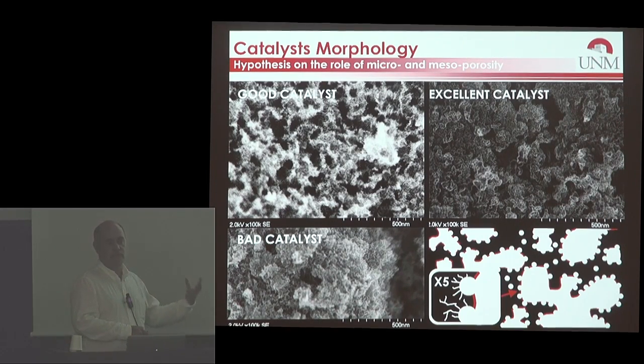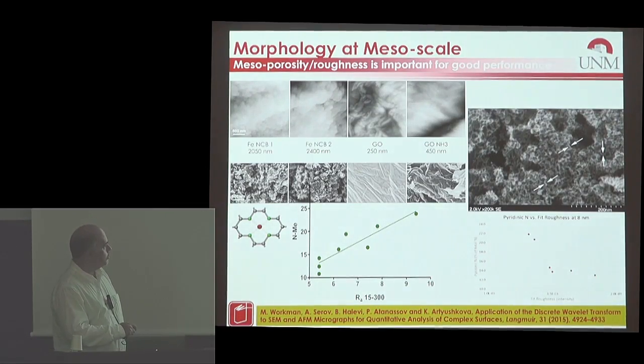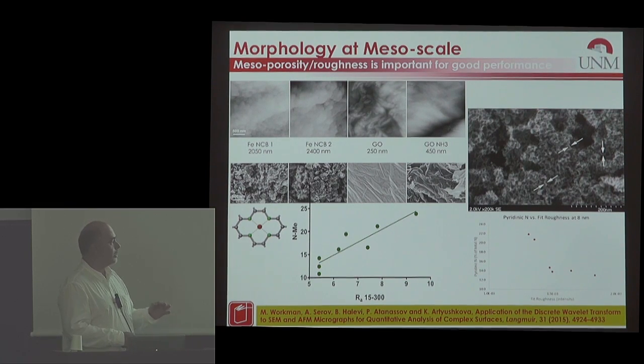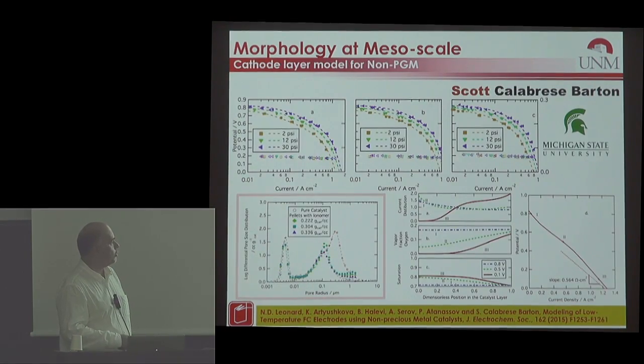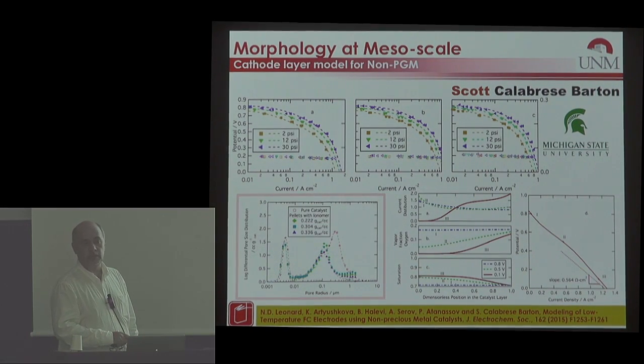In order to get out of this personal perception, we have developed methods of linking image analysis to local morphology and surface roughness, to calculate tortuosity and porosity of the catalyst from SEM images. And then we cross-reference this information with the microporosimetry of these catalysts. In both experimental and theoretical work with our partner Scott Calabrese-Barton from Michigan State, we have shown that the catalyst is very sensitive to the amount of micropores. And during the processing of the catalyst into layers, the mesopores of these catalysts are also undergoing a change.